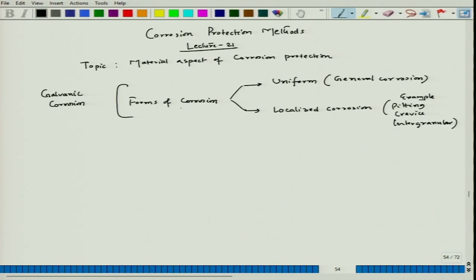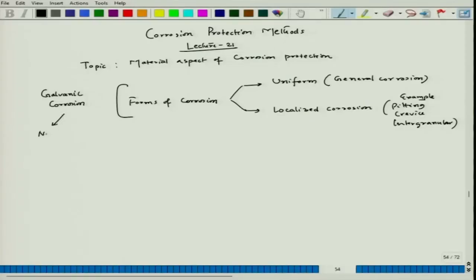Now, when we consider the form of corrosion like uniform, the galvanic corrosion happens statistically over the entire surface uniformly. So, we cannot decide which point would attack more and which point would attack less. So, finally, we get almost uniform attack pattern across the whole surface, but the start point is galvanic corrosion. That means where we have one noble component, one active component, and we have connection between these two.